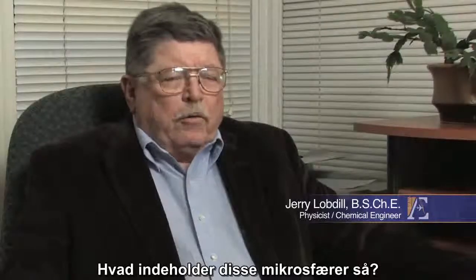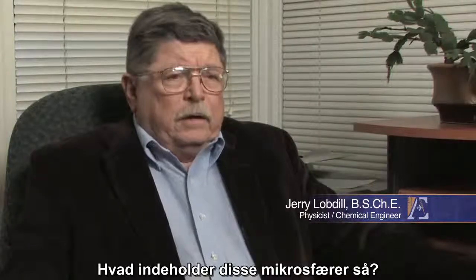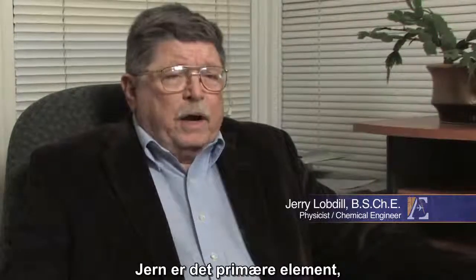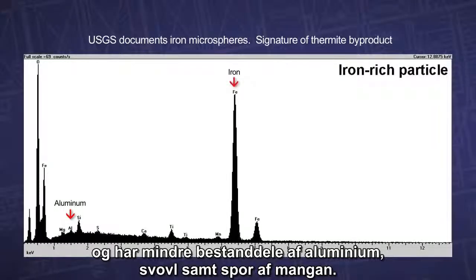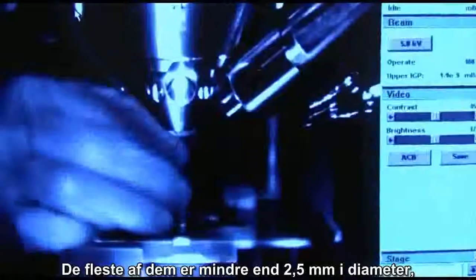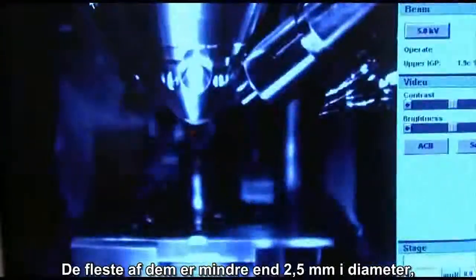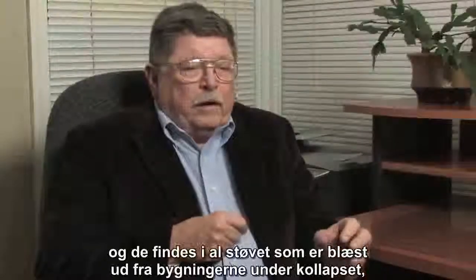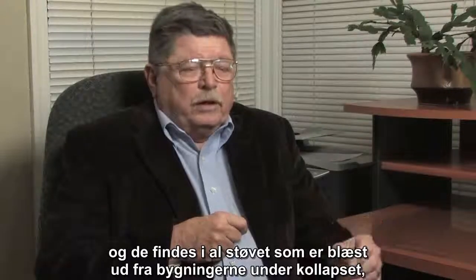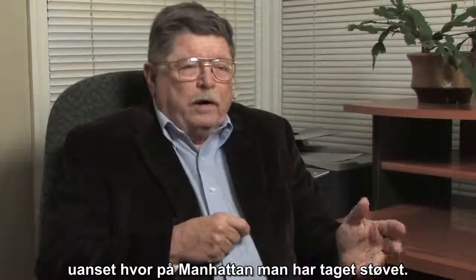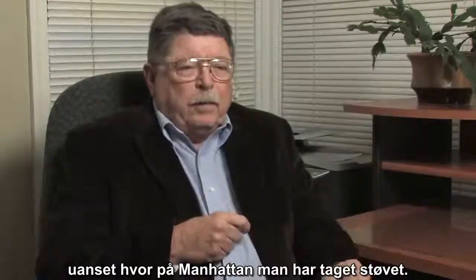So what do the microspheres contain? Iron is the main element, and then it has smaller portions of aluminum, sulfur, a trace of manganese. Most of them are less than about 1/10 of an inch in diameter, and they're spherical. And they're found in all of the dust blown out of the buildings during collapse, no matter where in Manhattan that dust is picked up.